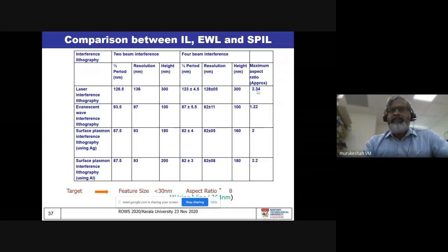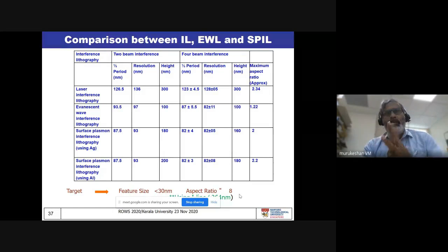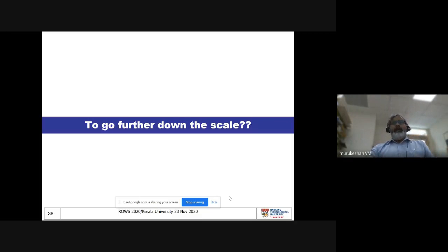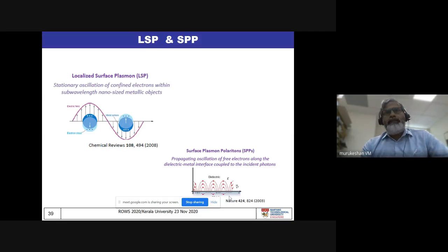But again, we are not near the value that we are supposed to achieve, and that is a feature size of less than 30 nanometer and an aspect ratio of approximately 8 using a near UV light source. We were using 364 nanometer. Okay, let us see what we can do. So here comes a lot of discussion and debate on how we can go further down the scale. Accidentally, we came across a very good paper, which I will show you after this slide.